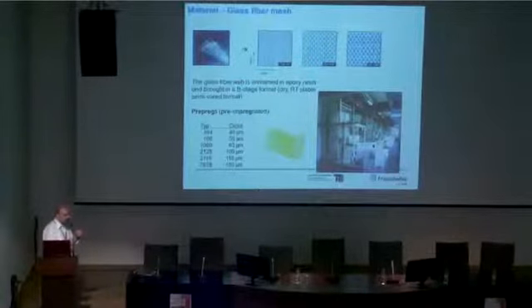The web of glass fibers dipped in the epoxy resin is then semi-cured at about 100 degrees Celsius in a B-stage format. This is very important in order to handle this prepreg. We call it prepreg. If you bring it to a B-stage format, you can keep it refrigerated and use it within the allowed time for usage. It is absolutely stable at room temperature, and then you can do further work making the FR4s.